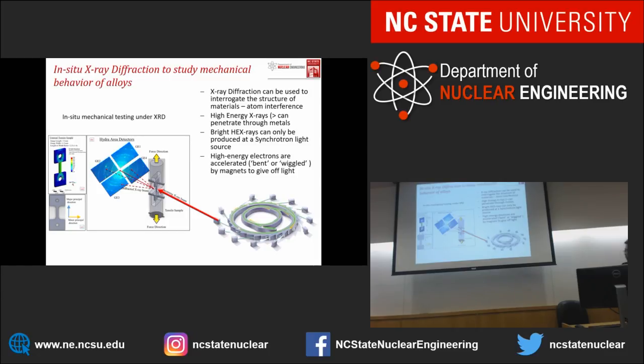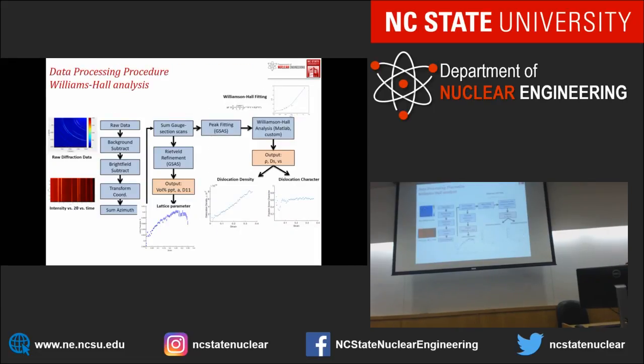As you can see from this illustration, we perform mechanical testing, and meanwhile, the incoming X-ray beam allows us to get diffraction patterns showing us rings. The collected X-ray diffraction data can be treated by a series of very complex steps, and the final result allows us to understand how the lattice parameter and the dislocation density evolve as a function of the strain.